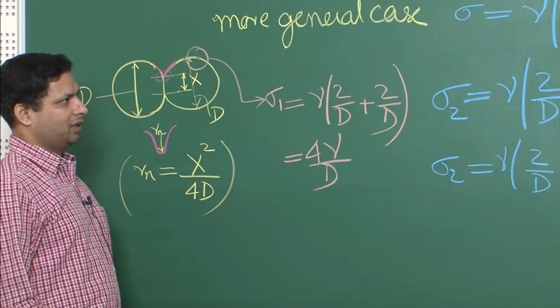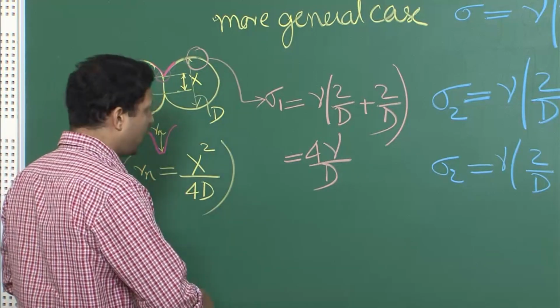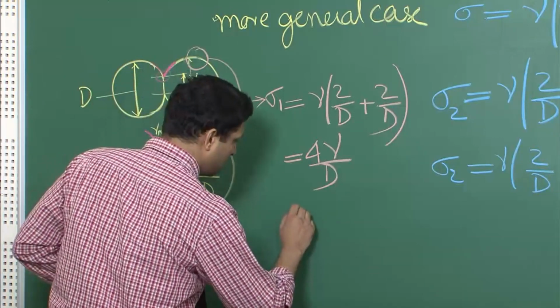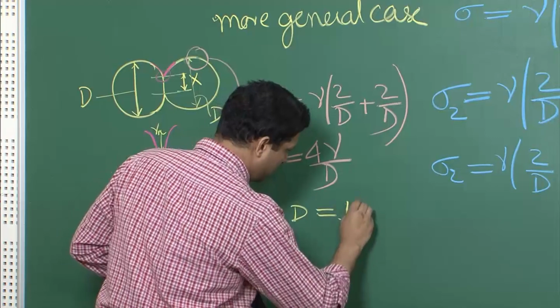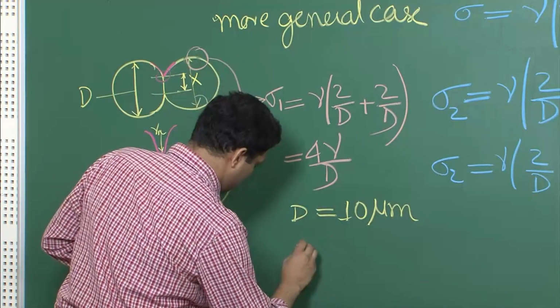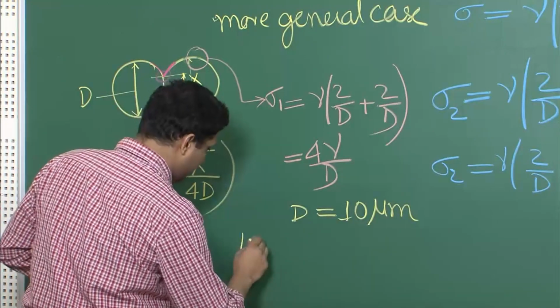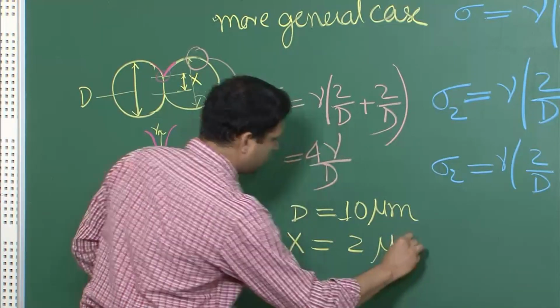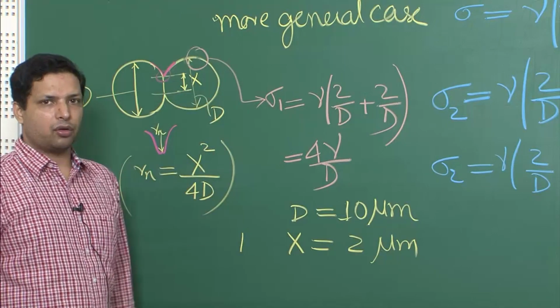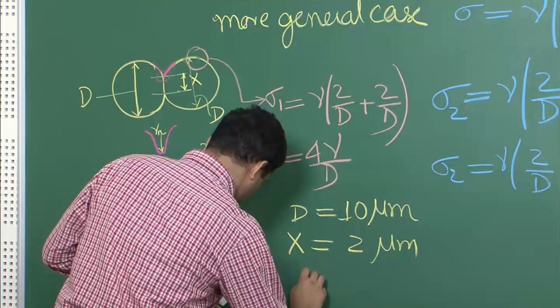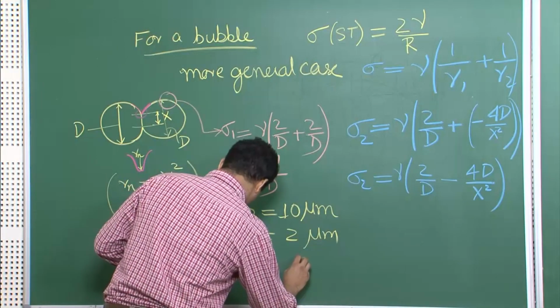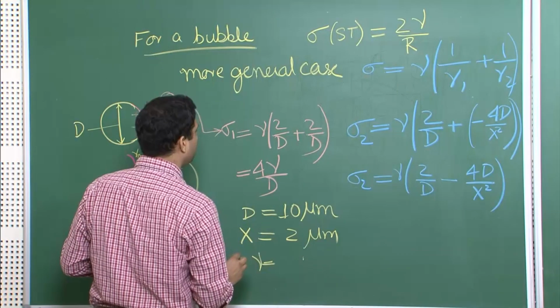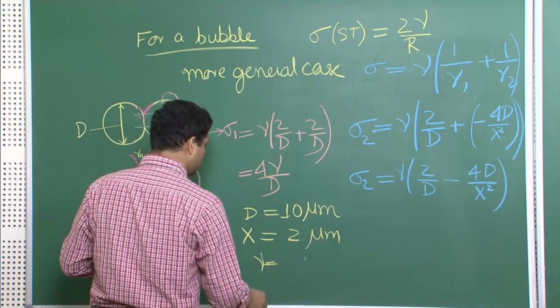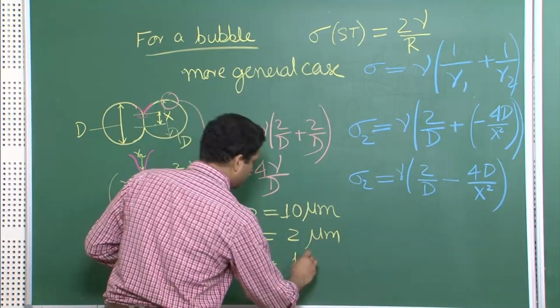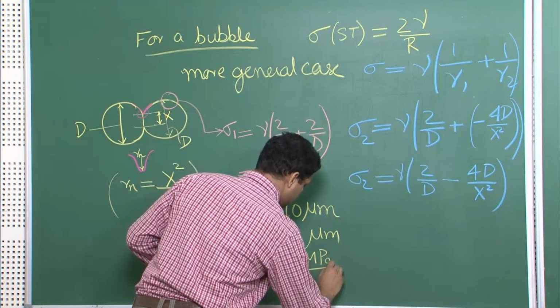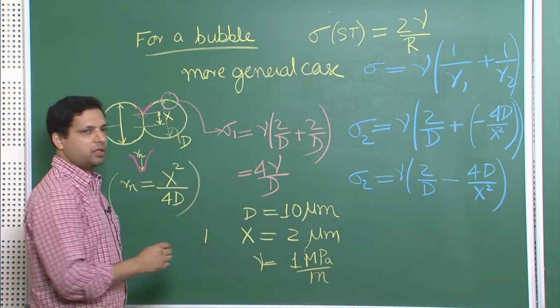Now, at this point let us take some typical values. So, let us say we have particle size d equal to 10 micrometer, and neck diameter, or basically x, let us say x is equal to 2 micrometer. So, we are saying this is 2 micrometer and this diameter is 10 micrometer, and gamma, let us take gamma equal to some value, let it be 1 megapascal per meter, because surface tension is per unit length.